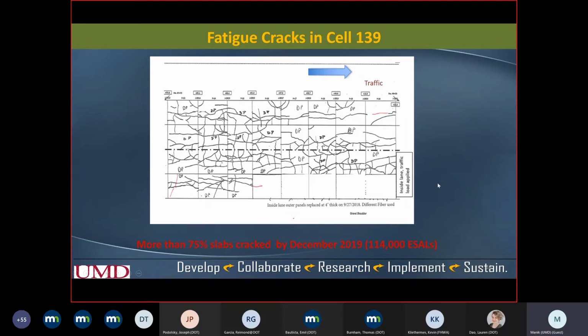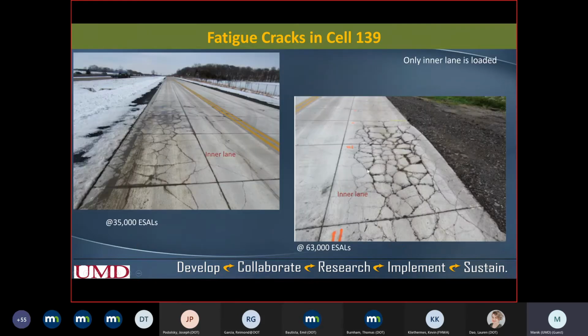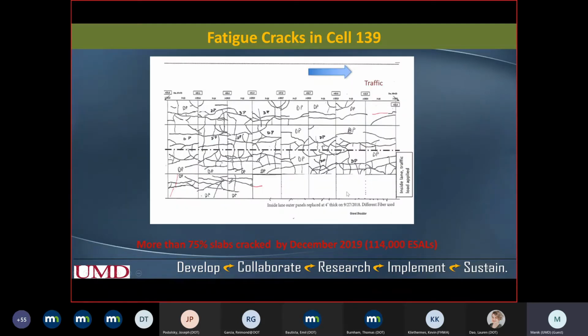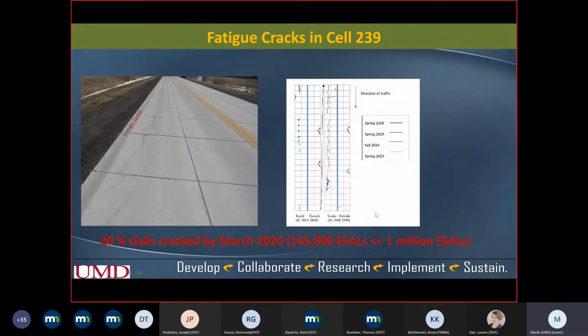So cracks all over. And then in 2018, some of these slabs, I think 14 slabs, were replaced with 4-inch thick pavement. Now on cell 239, which was 4-inch thick, we saw far less cracking. You can see longitudinal cracks, and at the end of the research study, in the data collections we had on the cracks, we saw like 70% of slabs already cracked by March 2020, which was after 145,000 ESALs.